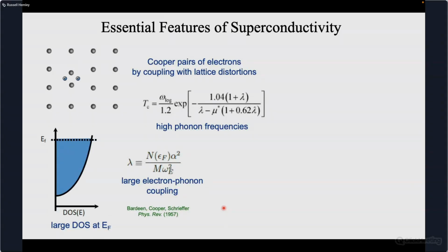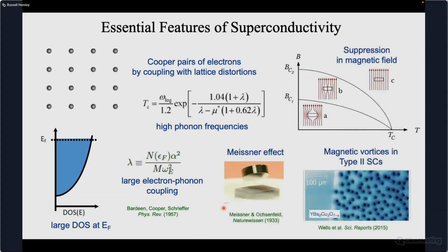You have the formation of Cooper pairs. In this theory, there's a coupling with lattice distortions. This would be enhanced. The TC would be enhanced by high phonon frequencies and a large density of states at the Fermi level. This is really the foundational idea, coupled with a gap in the system that gives you superconductivity.